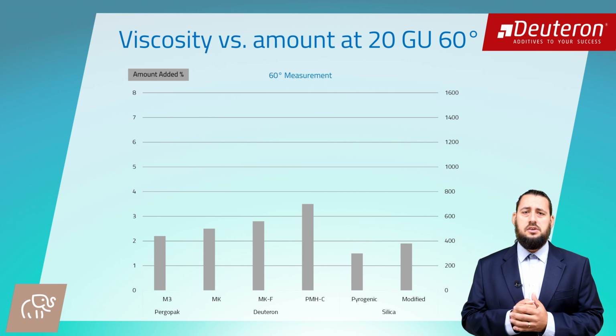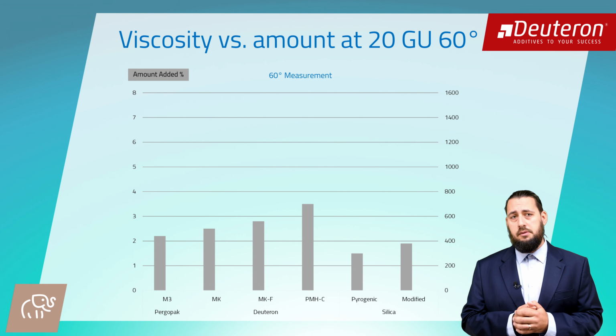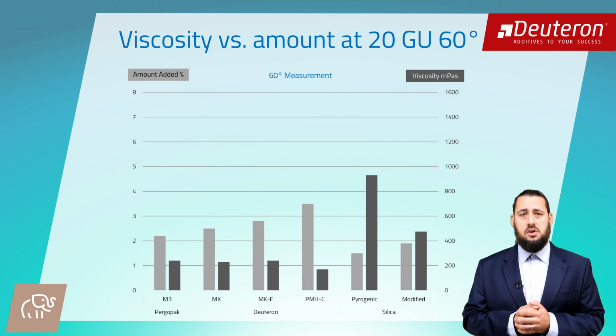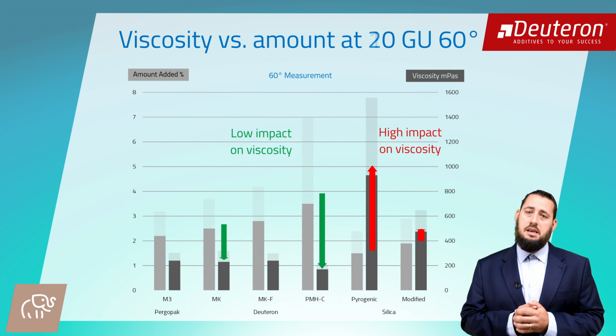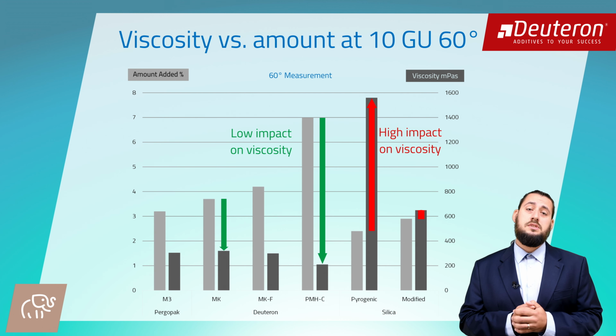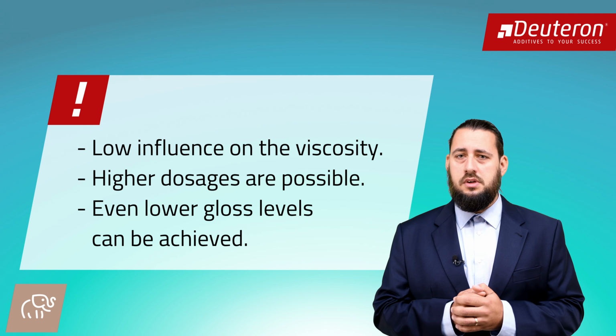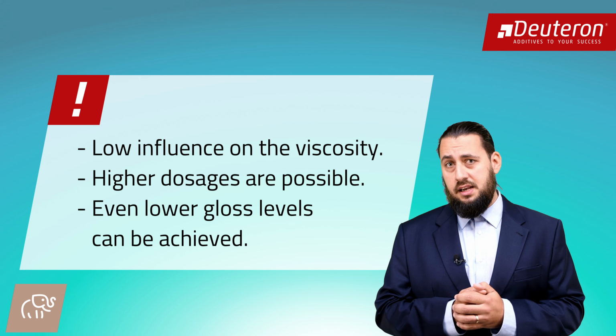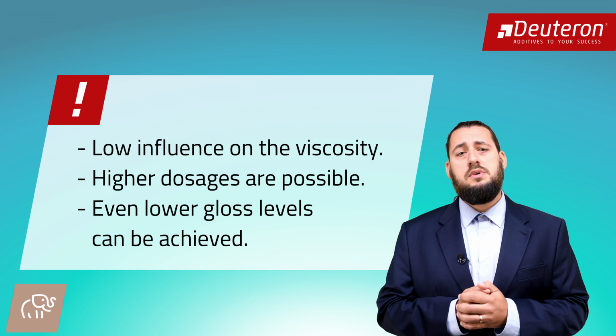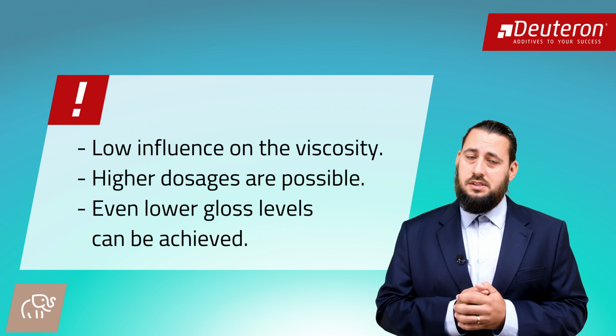The left axis shows the amount of matting agent in light gray. The right axis is the resulting viscosity in dark gray. All organic matting agents require relatively high amounts, but the viscosity remains lower compared to silica types. The same happens at 10 gloss units, but even stronger. This means that often lower gloss levels can be achieved compared to silicas because significantly higher dosages are possible with organic matting agents while the viscosity remains low.